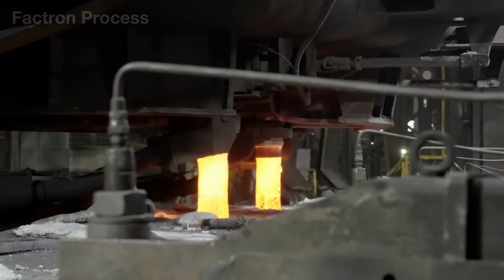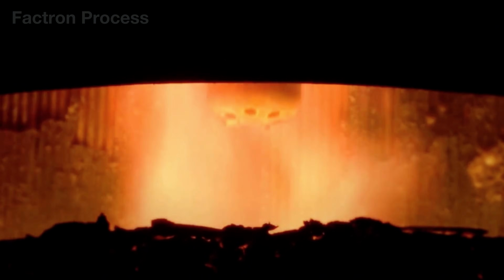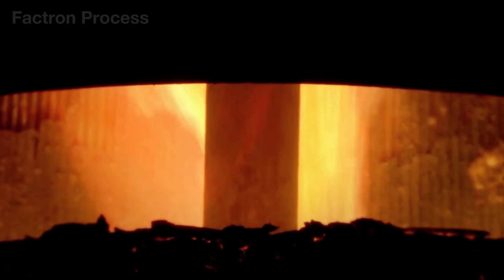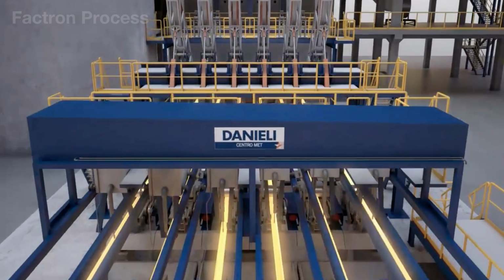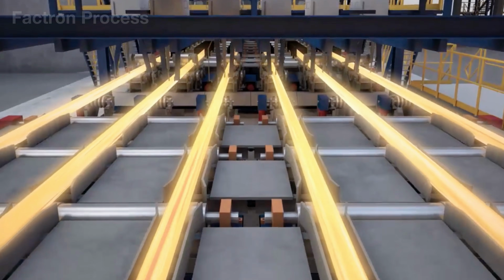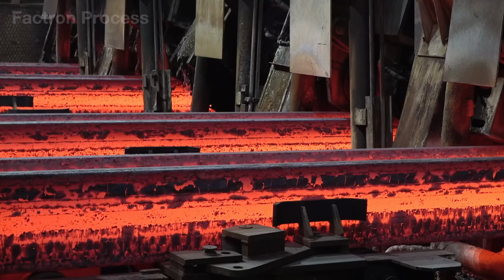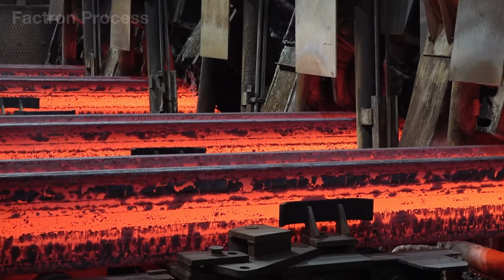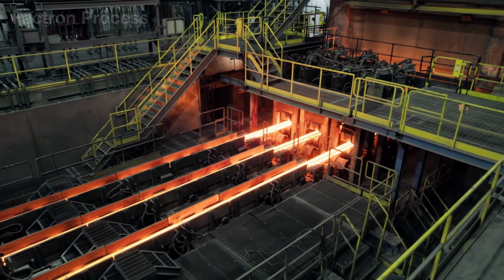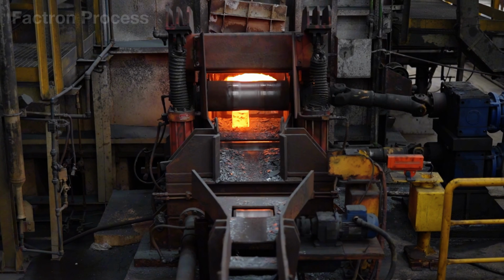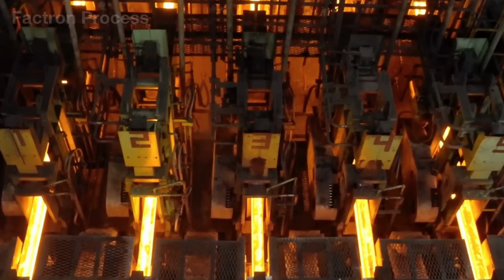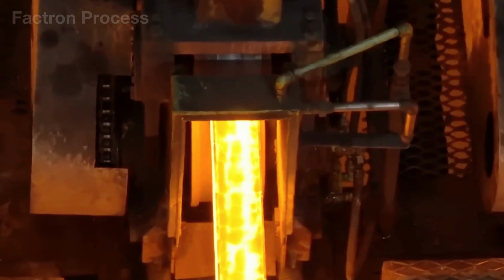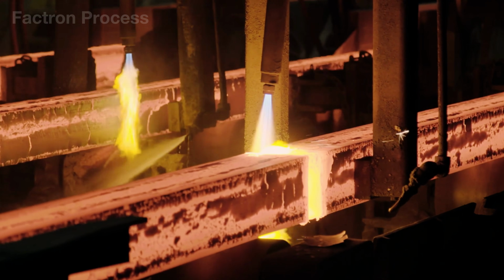A series of rollers continuously withdraws the strand from the mold and guides it through a mist cooling zone, allowing it to solidify gradually from the outside inward. Near the end of the process, the rollers apply gentle pressure to compensate for shrinkage and reduce internal porosity or centerline segregation. Once fully solidified, automated oxy-fuel torches cut the strand into large blooms approximately 13 to 20 feet long.